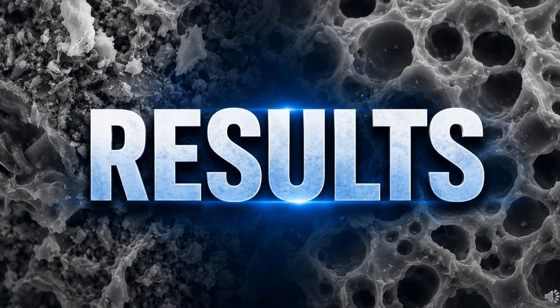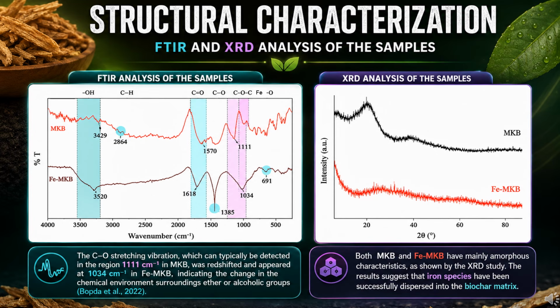Now, let's unveil the exciting results of our innovation. The figure here shows the FTIR and XRD patterns of mango kernel biochar and iron-decorated mango kernel biochar. Following iron impregnation, the FTIR spectrum of Fe-MKB revealed distinct differences that confirm successful modification. For Fe-MKB, the appearance of a weak Fe-O bond at about 691 was evidence. The shift in C=O stretching vibration at 1570 for MKB and 1619 in Fe-MKB proved the formation of Fe-O-C bond. While for XRD analysis, the lack of crystalline phases in Fe-MKB showed a well dispersion of iron oxide or nanosized structures.